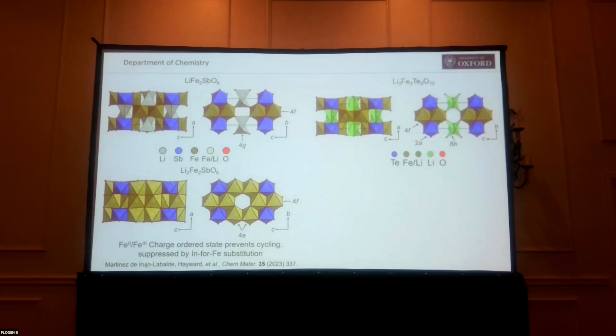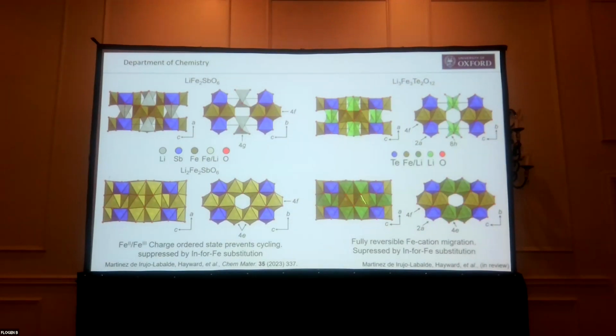Now, we're getting this iron migration problem. Now, in this material here, the issue is that we actually end up with a charge ordering between iron ions, and that's so stable that we can't actually take the lithium out. So this is quite good. But what we find is by substituting some of the iron with indium, we can break up this charge order framework and cycle the iron. In a related system, now we have tellurium, it's the same framework. Now we find we have a pretty reversible iron migration.